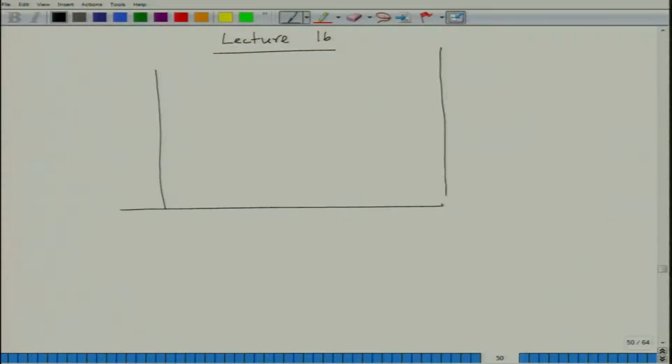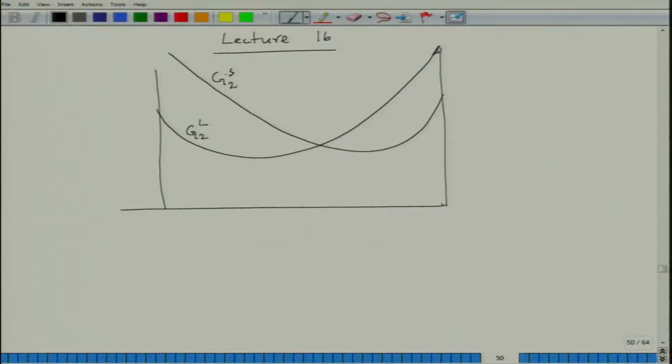So, what we have seen, if we draw the free energy composition graph, if this is my liquid line, this is G2 of liquid, and this is G2 of solid, at a particular temperature T and pressure, the equilibrium compositions can be seen from the common tangent on both the free energy lines. And this is my equilibrium XB liquid, and this is XB solid.